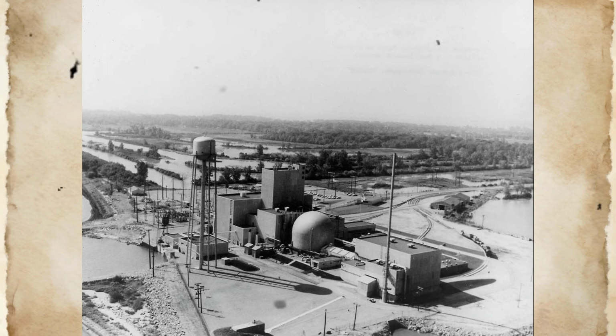Cover gas samples from the argon atmosphere maintained above the sodium coolant provided additional forensic evidence about the fuel damage through detection and analysis of gaseous fission products that had been released from breached fuel pin cladding. The isotopic composition and activity levels of noble gases, such as xenon and krypton, allowed investigators to estimate the approximate number of fuel pins that had experienced cladding failure and to determine the general time frame over which the damage had occurred based on the decay characteristics of short-lived isotopes.